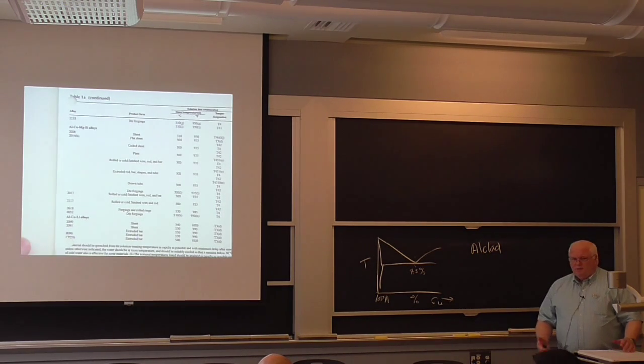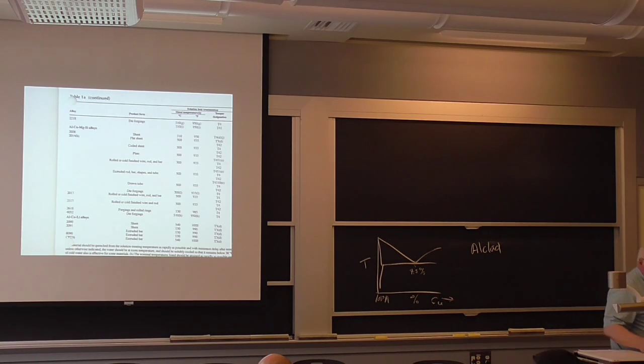Okay. Lithium actually has an interesting property in that it's lightweight and it reduces the density of aluminum by 10%. It also increases the Young's modulus of the material by 10%. And E over rho is the important parameter for structural stiffness. So if I want to have something that's slender and stiff, I want a good E over rho, and lithium alloys can give me 20% more than typical aluminum alloys.